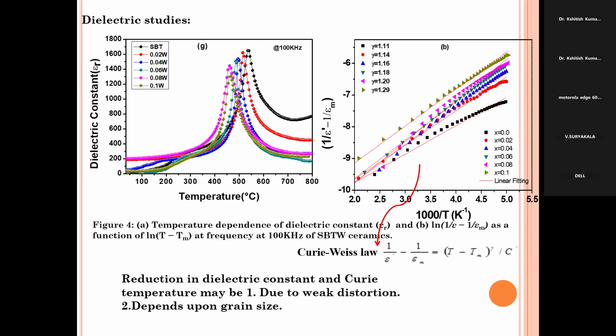Coming to the dielectric study, we took the dielectric measurements with an LCR meter and plotted the dielectric constant with respect to temperature. We got a peak point, which is called the transition temperature. That means the ferroelectric to paraelectric transition: at a particular temperature, all ferroelectric materials become paraelectric, and that is called the transition temperature. From the dielectric study we found that the dielectric constant gradually decreases, and then we have to find out the second graph, that is the diffusivity.